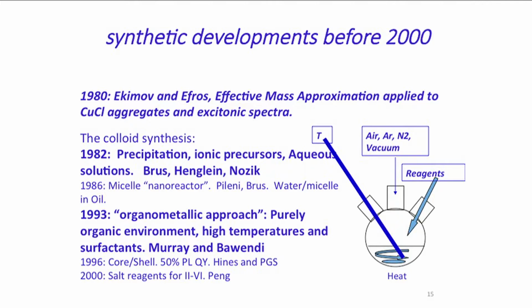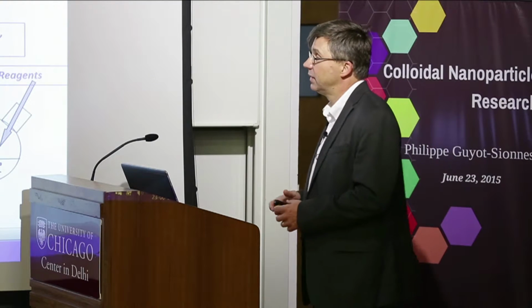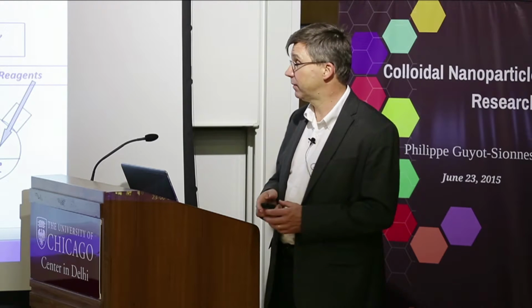Soon after, the colloidal synthesis in solution really emerged through the work of Louis Brus, Armin Henglein, Arthur Nozik, and several others. And there was another technique, micelle nanoreactors, by Marie Pileni and Louis Brus. And in 1993 is the work that I mentioned, the work by the group at MIT, led by Moungi Bawendi. There, they completely changed the way we look at the synthesis. They used an organometallic approach, which involved toxic, very toxic and pyrophoric reagents. And so they were very brave, and they also were very adventurous in trying different things. But it worked beautifully. It gave the best results.